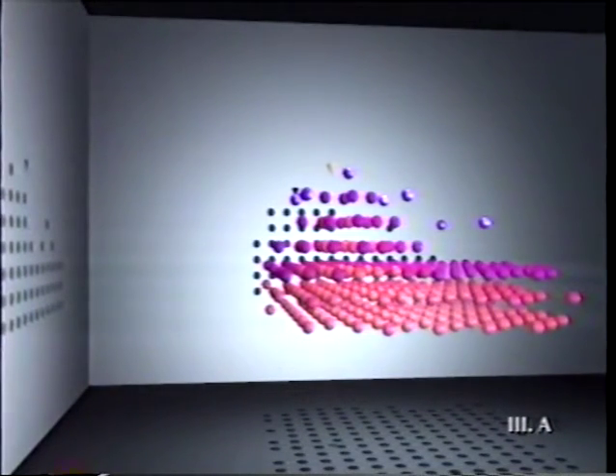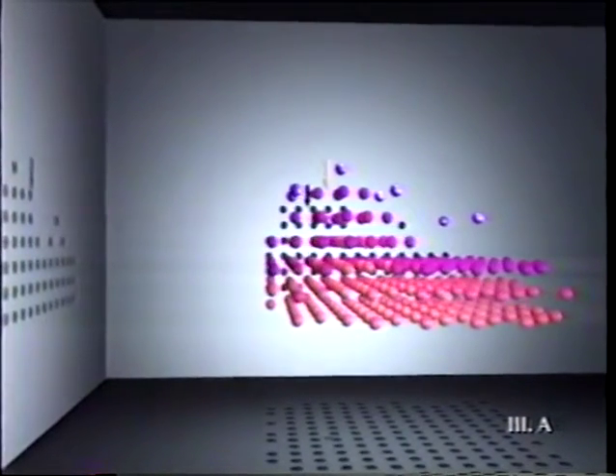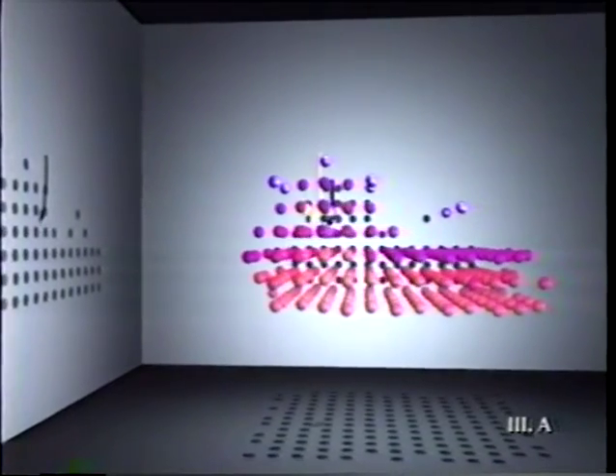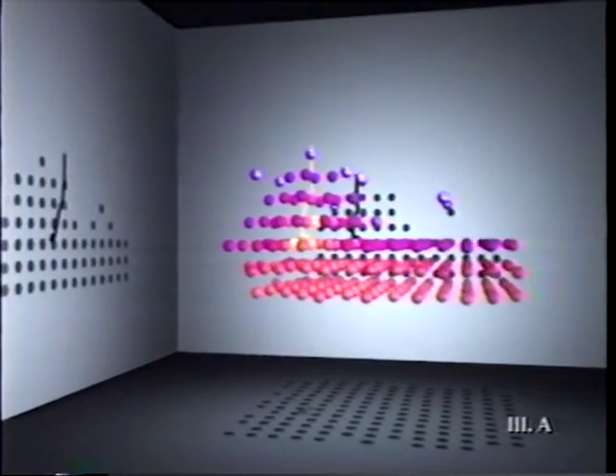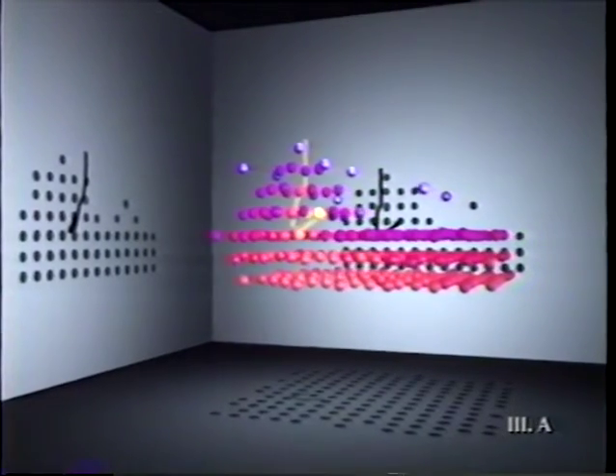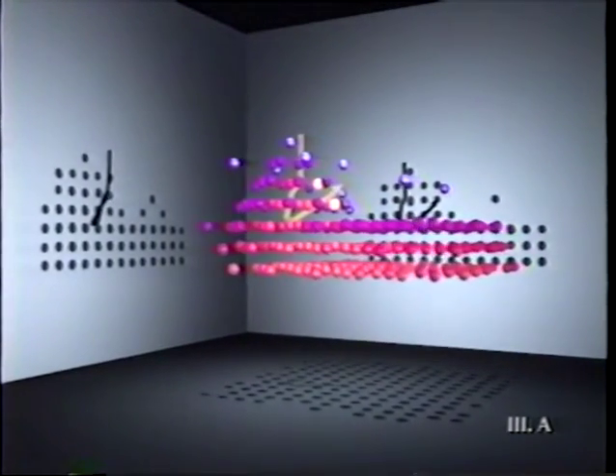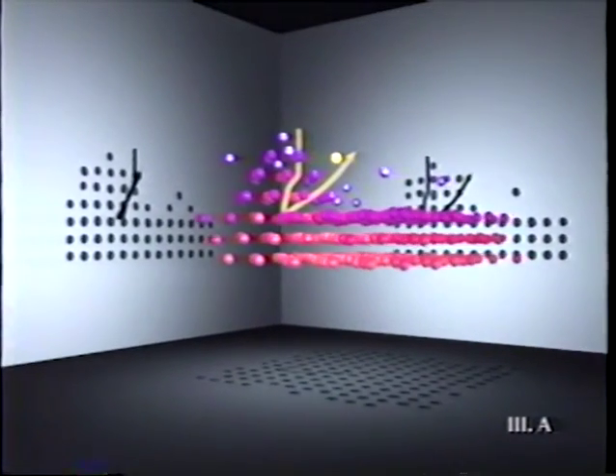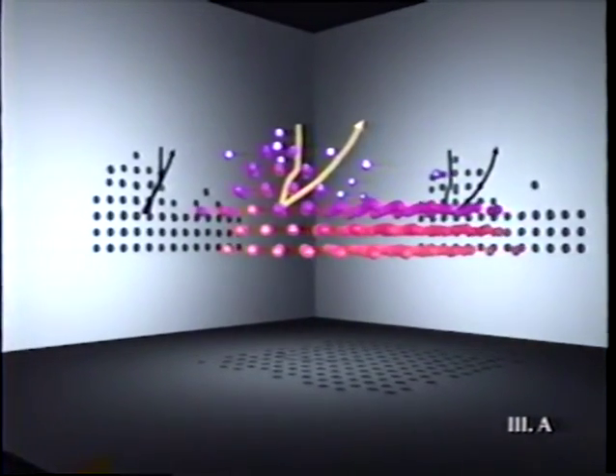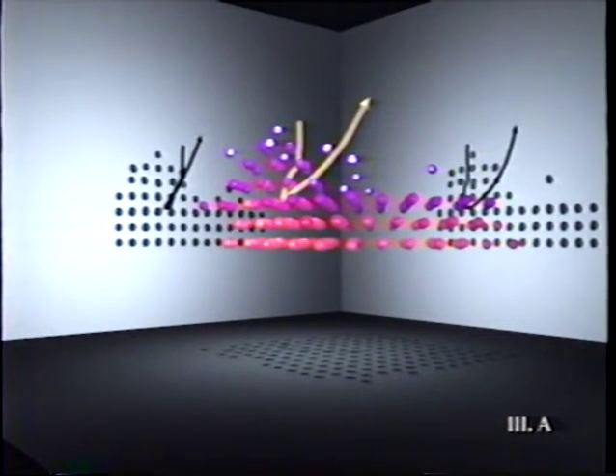This first simulation shows a reflection. The 10 eV hydrogen atom is normally incident on the surface, pointing into the pyramid-like surface feature. As the atom passes through the lattice and comes close to a number of nickel atoms, the potential energy of those nickel atoms changes dramatically. The change from blue to yellow represents approximately 2 eV of energy. Of course, for every action caused by the hydrogen atom to the lattice, there is a reaction force on the hydrogen atom. In the visualization, the hydrogen atom's color does not change.